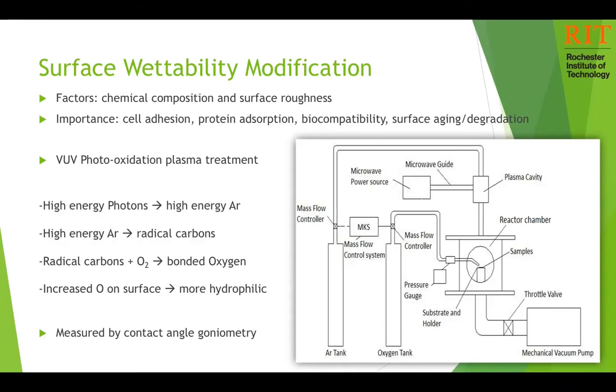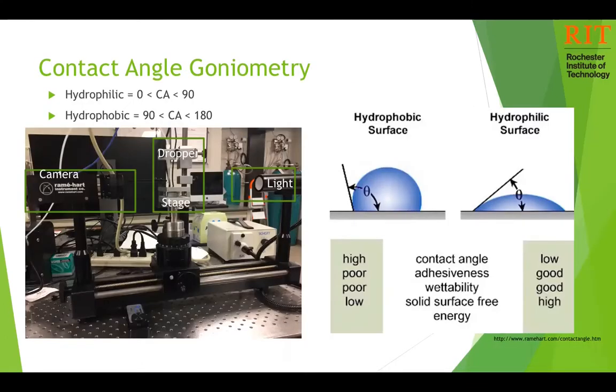Wettability and hydrophilicity are commonly measured using contact angle goniometry. Here we have a diagram of a contact angle goniometer. In general, the way it works is an automatic dispenser is used to place a drop of water onto the surface of the material. We use a hot press to create polyester films, which are then placed on the sample stage. A live feed camera is trained on the drop and the sample stage and adjusted such the camera can take a clear image of the drop. The software then calculates the angle at which the drop rests on the surface of the polymer film.